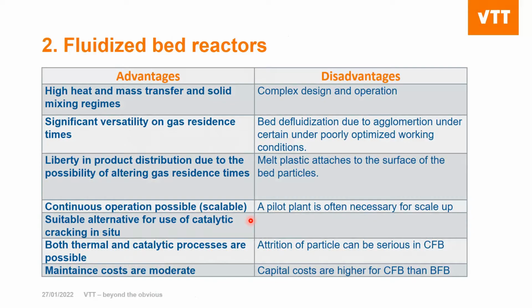Let me talk about the advantages and disadvantages of this type of reactor. Fluidized bed reactors have high heat and mass transfer and good solid mixing regimes. You can vary the gas residence time in the reactor by adjusting the flow of fluidizing gas. If you have low fluidizing velocity, then you have higher residence time, and if you have higher fluidizing velocity, more gas, then your residence time in the reactor is decreased. So you can vary that by changing the fluidization gas. The product distribution can be flexibly changed depending on what kind of gas residence time you choose. Then it's possible to operate this type of reactor continuously, and it's scalable.